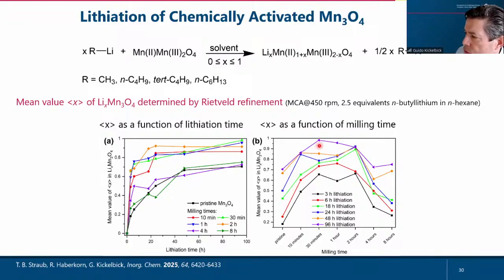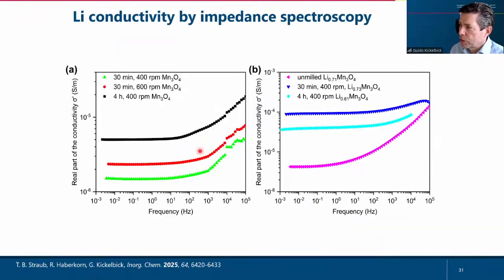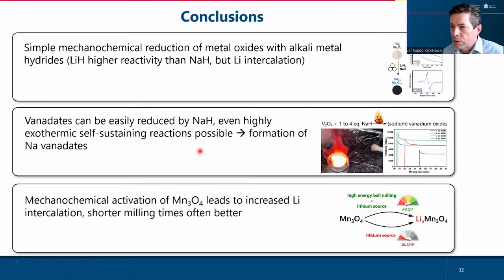This is just to show you again that long milling times do not always improve the results, but after short milling times, you always get, in most of the examples already, very nice results during this chemical activation or mechanochemical activation of the manganese oxide. And again, we could prove by impedance spectroscopy that we have better ionic conductivities in these cases. Okay, and with that, I want to conclude.